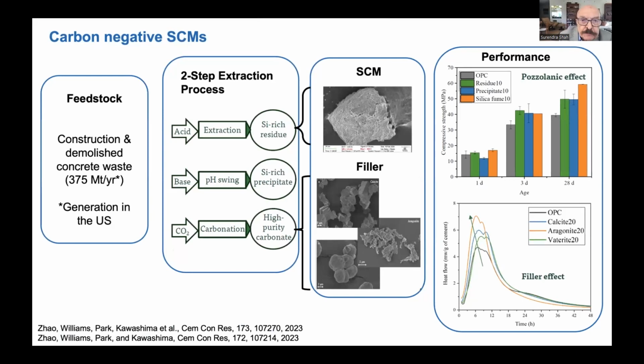First, you reduce pH, and that produces this silica-rich supplementary cementitious material. And then you increase pH, accelerate carbonation, and they have shown they can produce independently each of the polymorphs of calcium carbonate. And if you add this supplementary, I call it carbon negative cement material, then you can see you can increase the rate of hydration and increase, for example, compressive strength. So this is a very innovative, useful product where you take construction waste and with two-stage extraction, you produce supplementary cementitious material and single polymorph calcium carbonate.